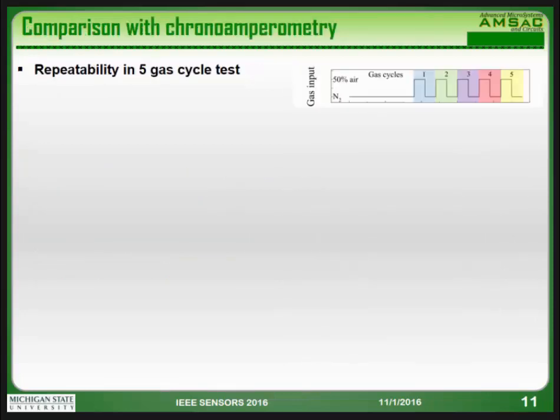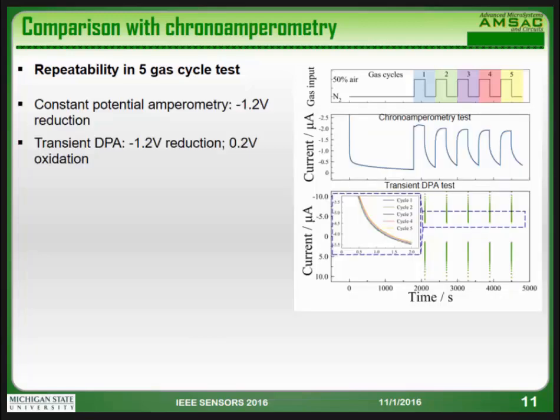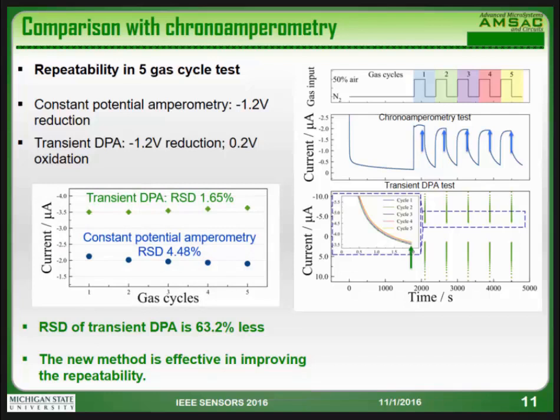Then we compared our method with the constant potential amperometry. The test is performed with 5 gas cycle tests. Here shows the gas input. We alternate nitrogen and 50% air. And here shows the response of the constant potential amperometry and our method. The difference is that the transient method applies 2 potentials, and the constant potential amperometry only applies one potential. We also extracted the current signal, and we made a comparison here.